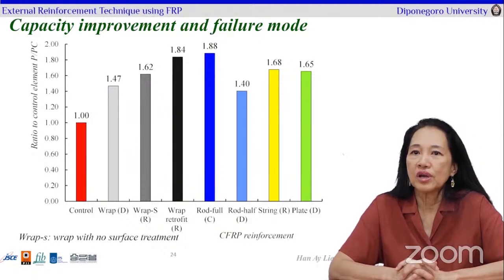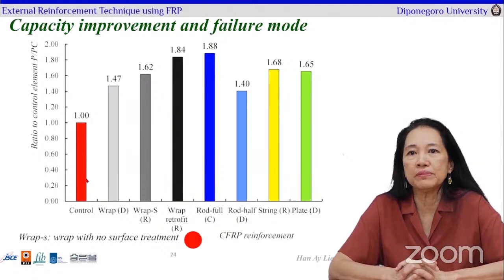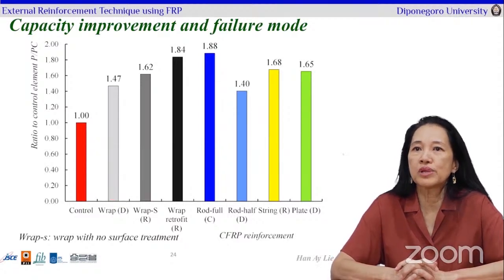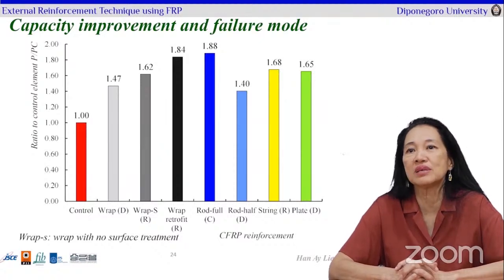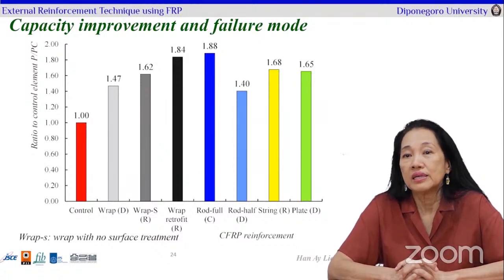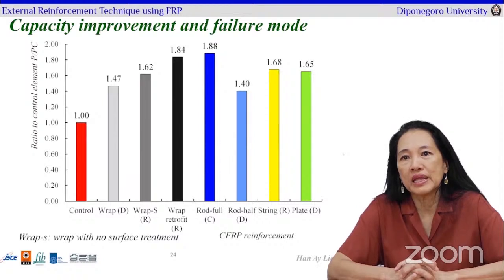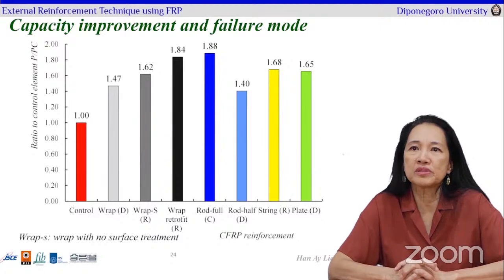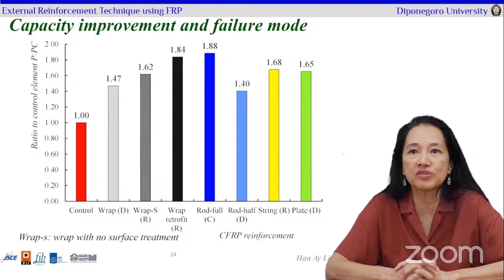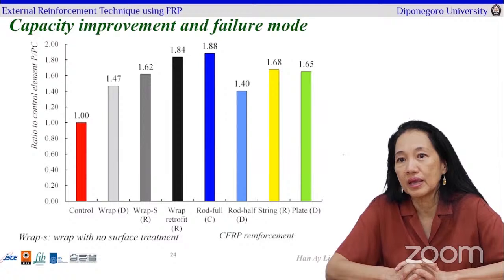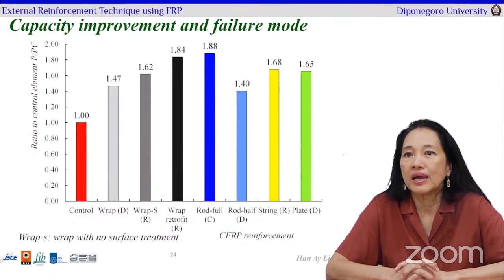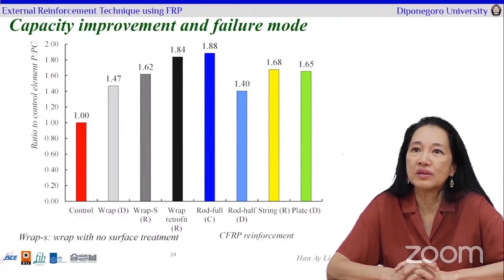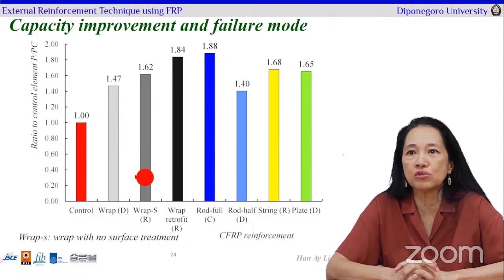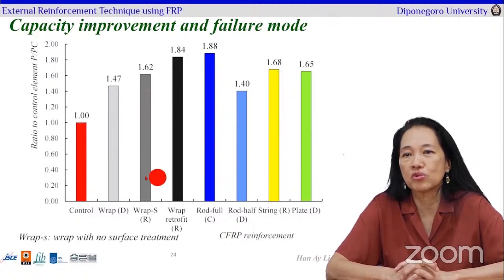Here on the left, we have the result of the control beam in red. We normalized it to the normal beam so that we directly can see the increase in capacity. The gray one is the wrap that underwent debonding. Still, you can see that there was a substantial increase of 47% to the normal beam. Then, with additional surface treatment, we had an increase of 62%, which is quite large.